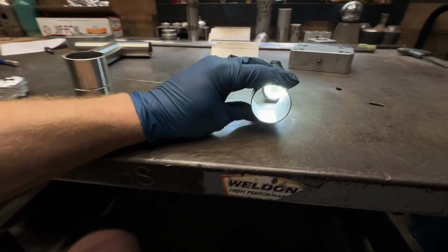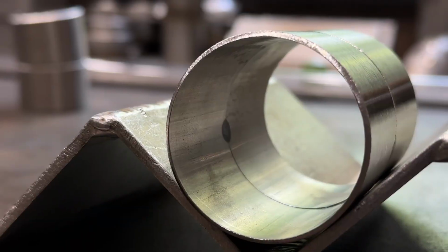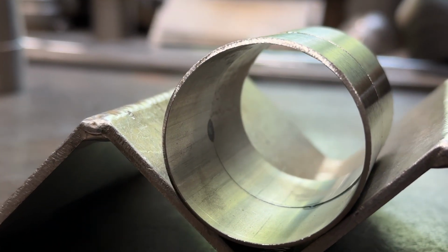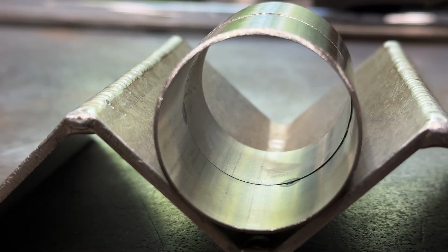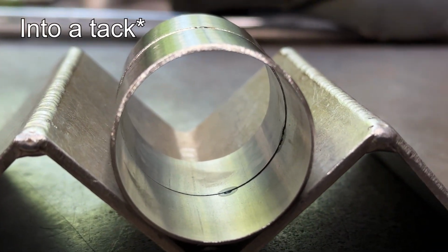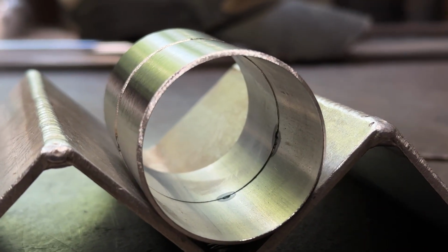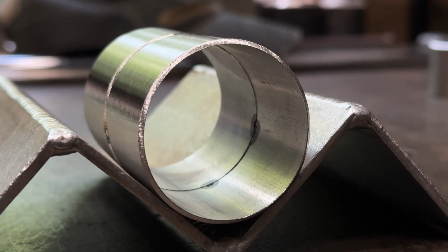And then if we look at the inside of these pieces, this non-purged one, if I zoom you guys in, then you can see the nasty oxidation on the inside. If you put a lot of heat into it without a purge, it's going to get through the tube and provide all that nastiness that we saw on the non-purged weld on the inside. And even if it's just a tack, you still will be running over that nasty oxidation on the inside and pulling that stuff into your nice clean purged weld if you go over top of it, following that sequence of operations, order of operations rather.